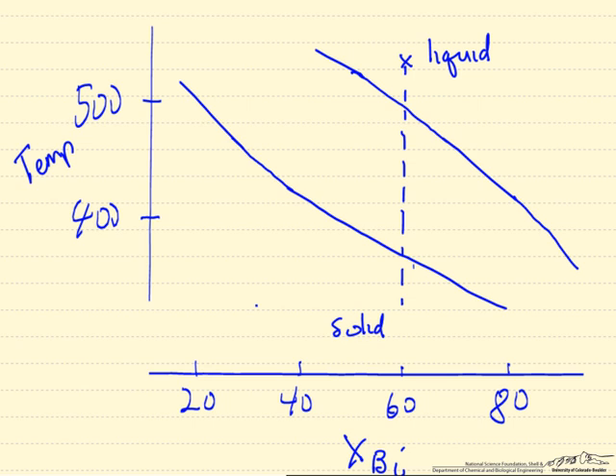Here we're starting with a liquid, we're going to cool it down, this region is solid. The region in between is the two-phase region, so liquid plus solid coexist in that region. When we cool it to this point, what I've drawn here is a tie line showing the solid phase that's in equilibrium with the liquid phase.